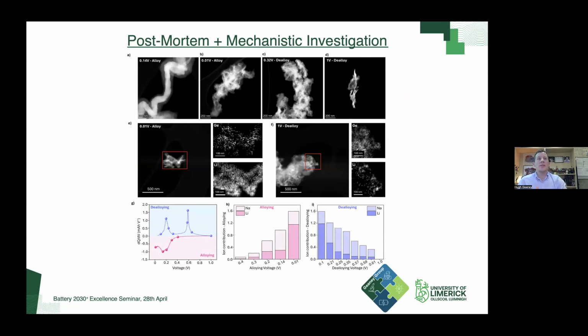Looking at the mechanism side of things, we had some challenges interrogating these using microscopy. You have overlap between germanium and sodium in the EDX energy range, and we also wanted to really prove that the lithium was active in the system. So we did some nice EELS analysis here. What we found was that we had lithium incorporated into the fully alloyed system, which was removed once we dealloyed it.